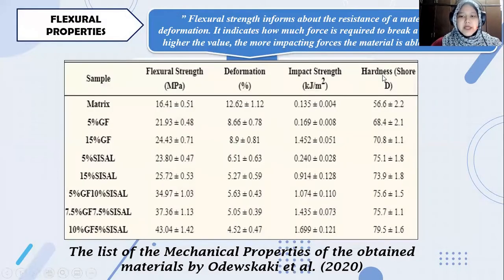Next, on the flexural properties. Flexural strength informs about the resistance of materials against deformation. It indicates how much force is required to break a test sample. The higher the value, the more impacting force the material is able to withstand. This is the list of mechanical properties of materials by Odewskaki et al. in 2020. With 10% glass fiber and 5% sisal fiber, they have the highest flexural properties among the other specimens. Thus, this proves that hybrid composite can also increase the flexural properties of the polyurethane.